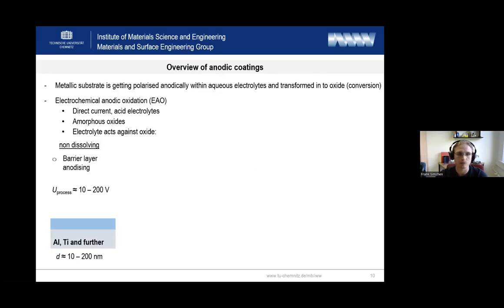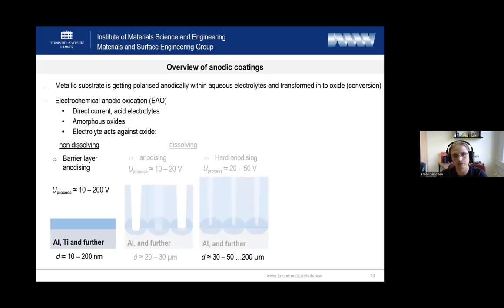And in case that we are using non-dissolving electrolytes, so electrolytes which cannot attack the oxide itself, and apply voltages between 10 and 200 volts, we carry out so-called barrier layer anodizing, which we know from interference coloring of titanium substrates, or for example for manufacturing electrolyte capacitors.